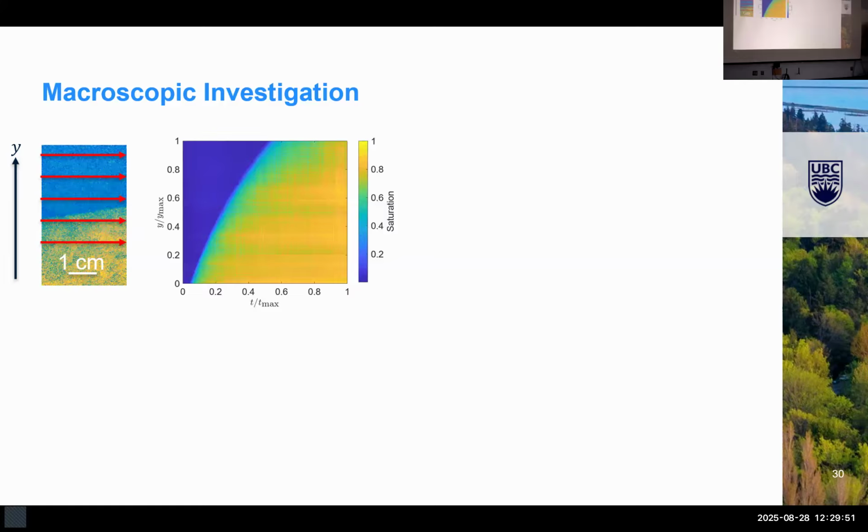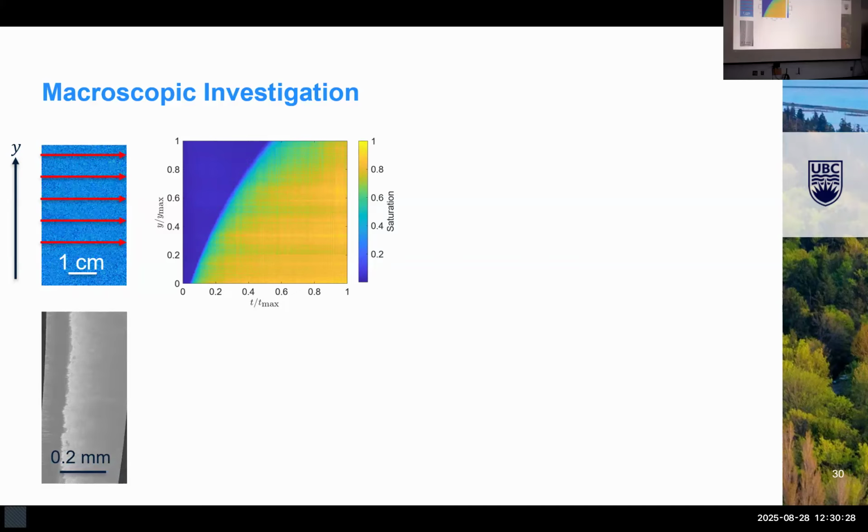We can average across that and look at it this way instead, as a spatiotemporal plot. And now you see the dry paper separated from this saturated region, from this sort of diffuse bluish green saturated wetting front moving through there. So just knowing what we know about the volumes of the different pore sizes in the paper, it's likely that all this yellow stuff is those big interfiber pores filling, and we can't get too good of a sense of what's going on inside the fiber wall specifically here, although it does give us a good overall picture of the saturation. But to figure out what's going on inside the fiber walls, we need to use a different type of measurement to give us an analogous quantity.